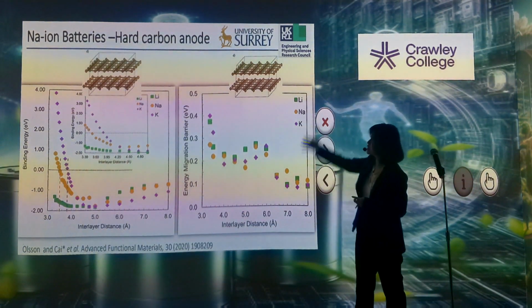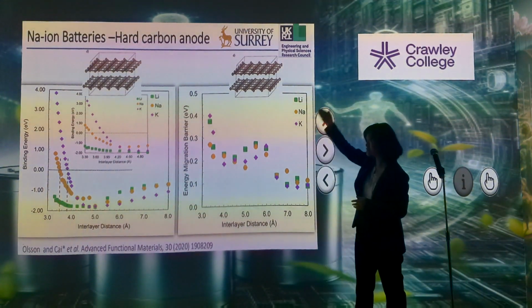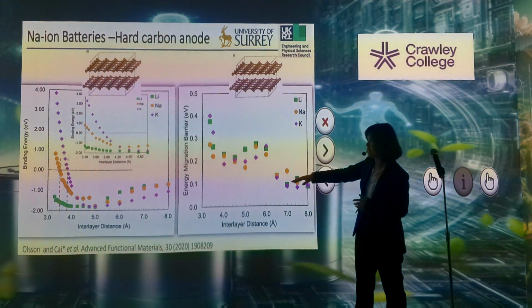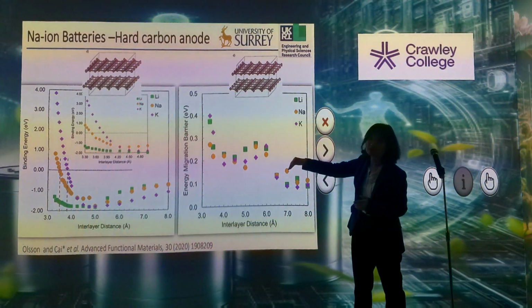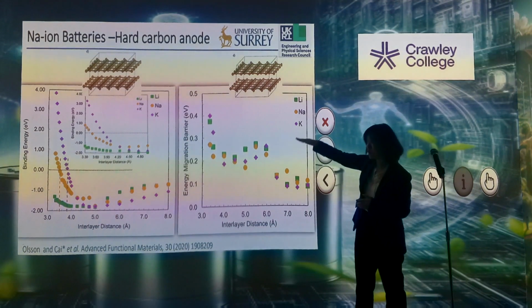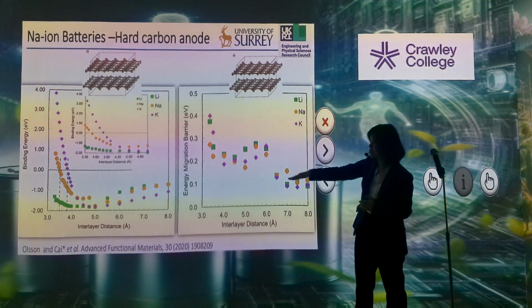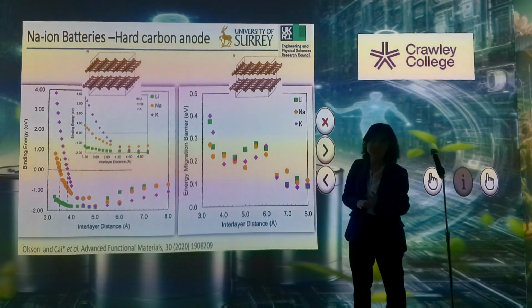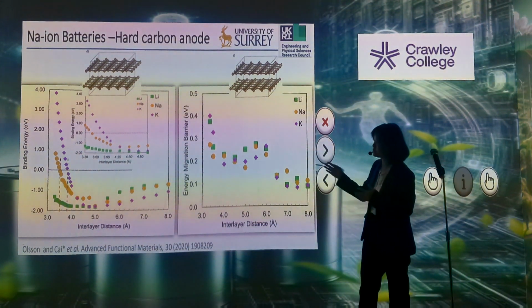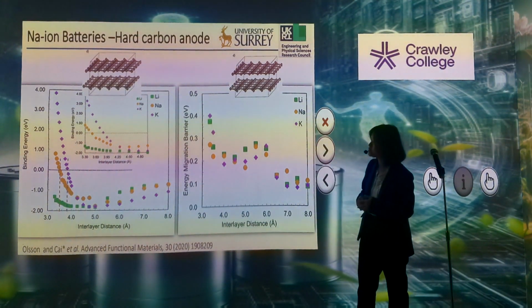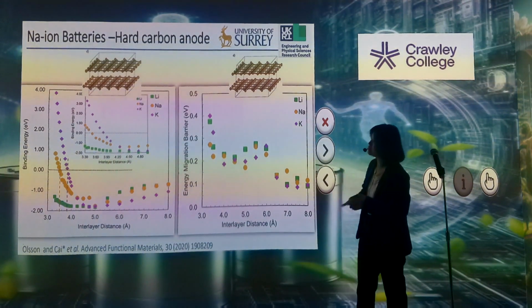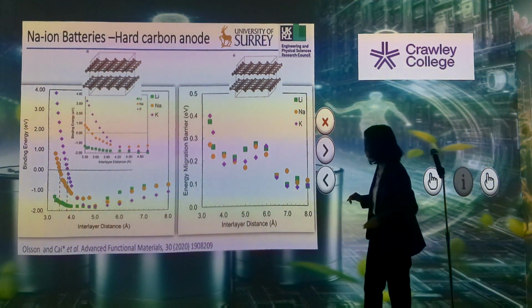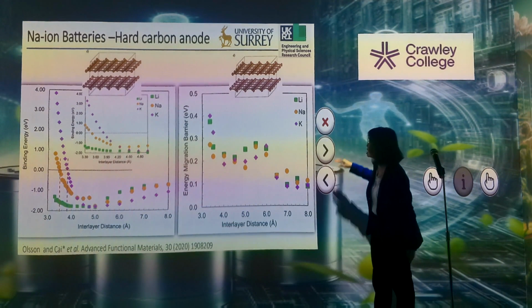We also looked at the interlayer distance of the structure, and we found that the favorable intercalation, which is when the energy is below the zero line, only happens at a certain interlayer distance for sodium and for potassium. But for lithium, it doesn't matter. You can put lithium into any interlayer distance.